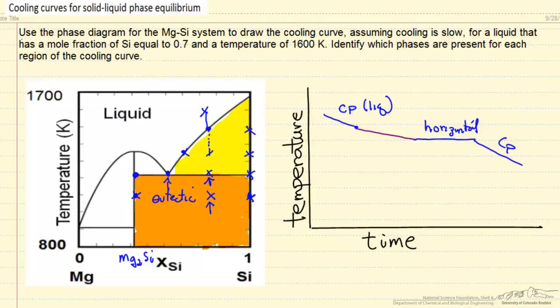The details are not strictly correct because I didn't look up heat capacities and heats of melting, et cetera. But the important points are here: the temperature decreases based on heat capacity. At this point it's a liquid, this is the heat capacity of the two solids. Here we have the formation of the compound and additional pure silicon. At the eutectic point, the temperature does not change. Here the temperature decreases as we form silicon solid from the liquid mixture.